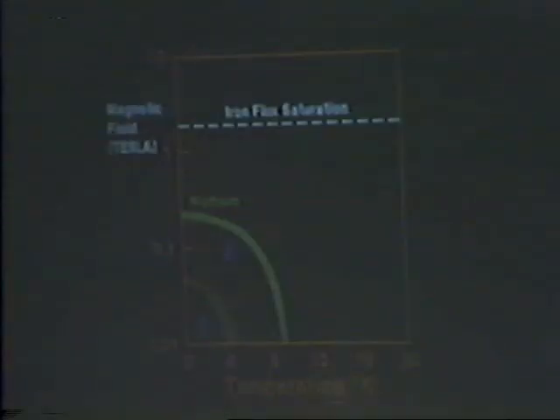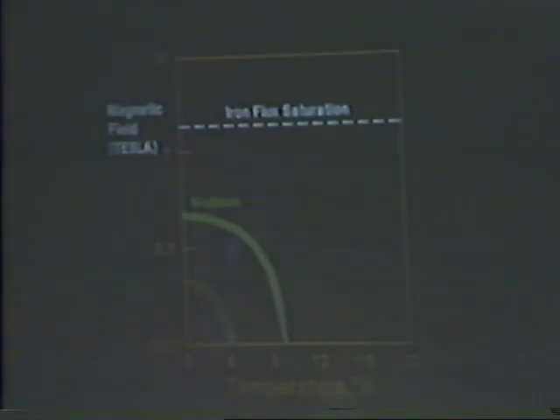If I could have the next slide. This illustrates the kind of magnitude of critical field that elements like mercury and niobium have. What the critical field means is that above that curve, above the green curve, the superconductivity in these elements was quenched and the normal resistance was restored. So you have a superconducting phase boundary, so to speak, below the curve. Well, these values are really rather low. I've shown dotted on that slide the level of the saturation field of iron.